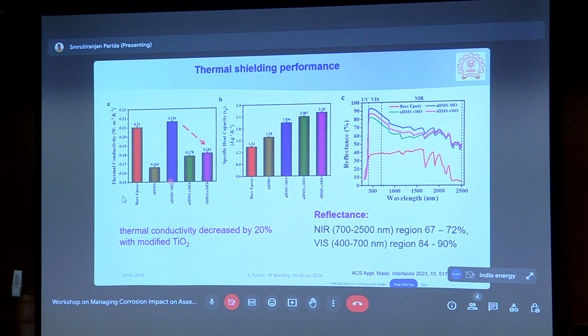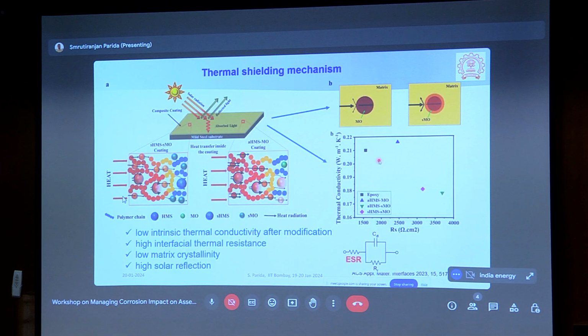So these two are very significant, indicating that the conductivity is decreasing the way we have modified the metal oxide and the way the HMS is higher. At the same time, this is the solar reflectance data that we can see here. In the NIR region, we are getting 60 to 70% reflection, even with the modified TiO2. And in the visible region, we are also getting 80 to 90% reflection of solar rays. The combined effect of low thermal conductivity and high solar reflectance is what resulted in a very good thermal shielding performance.